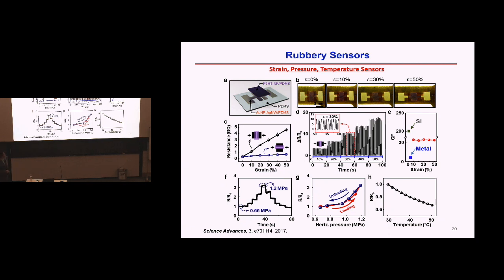For example, we can create physical sensors like strain, pressure, and temperature sensors, based on a two-terminal device architecture utilizing semiconductor sensing elements. Then we can test the device by mechanically stretching it. You get a fairly linear response of the resistance change, depending on which direction you stretch. You also get a device response that is repeatable cyclically. So this device can sense mechanical stretching or strain.